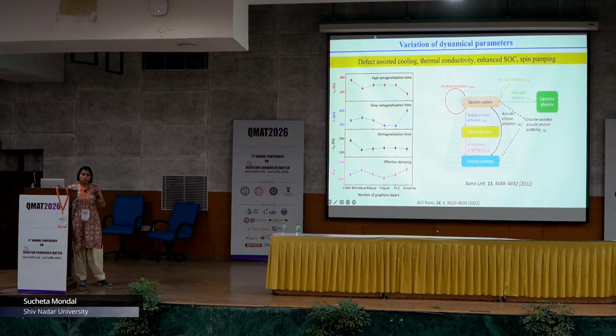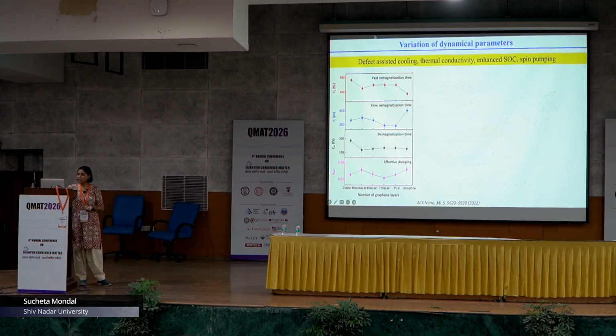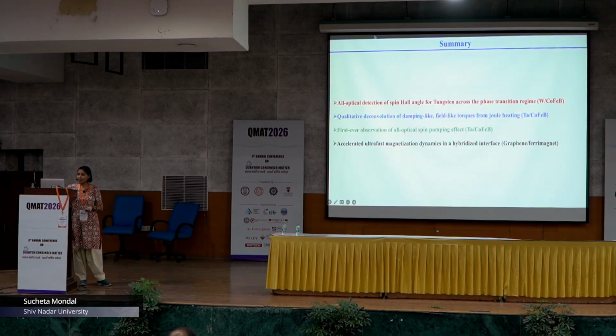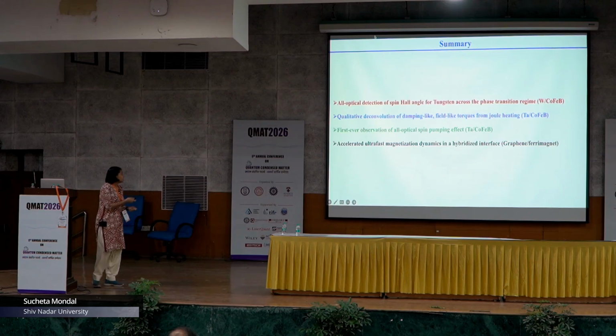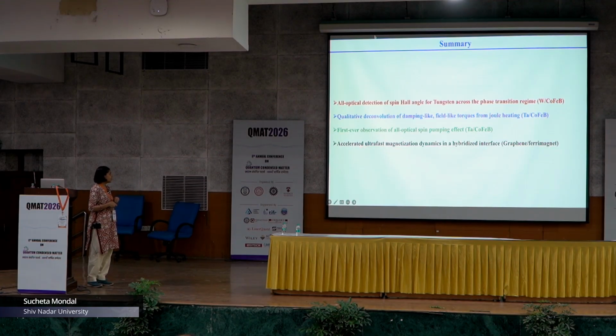Because of the time, I will be a little quick on this slide. If you have any question, please feel free to ask. The summary is that we have detected spin Hall angle by an optical method for tungsten. We also have segregated heating effect in tantalum and cobalt iron boron system, which can be modeled for other systems as well. There is a first ever observation of all optical spin pumping effect in tantalum cobalt iron boron, which we published in Science Advances at that time.